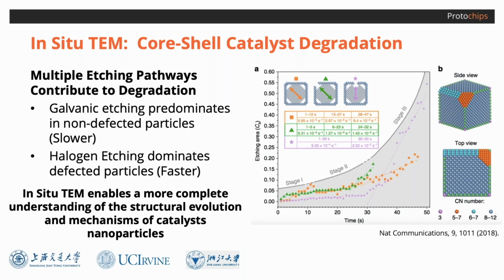However, if the platinum shell had defects in either the corners or along the terrace, that exposed the internal palladium to the electrolyte, and a much faster halogen etching process occurred. That resulted in collapse of the shell structure due to the pre-existing defects and a significant loss of catalytic activity.